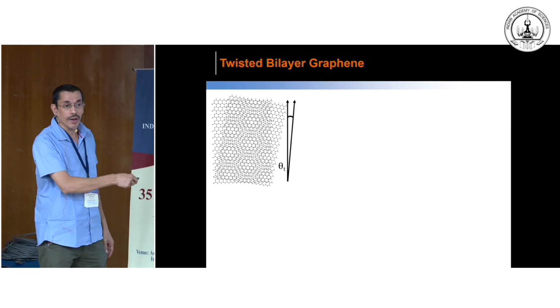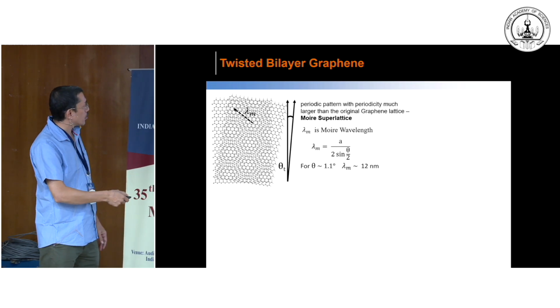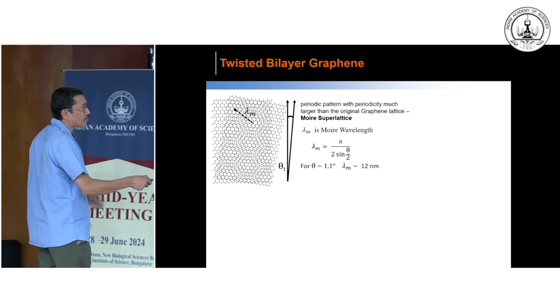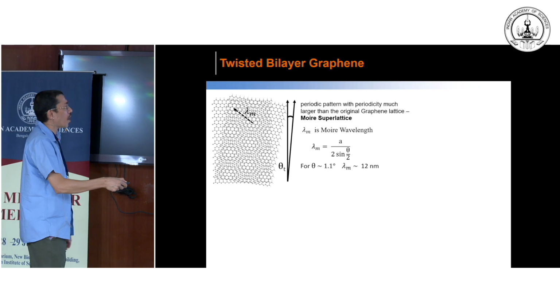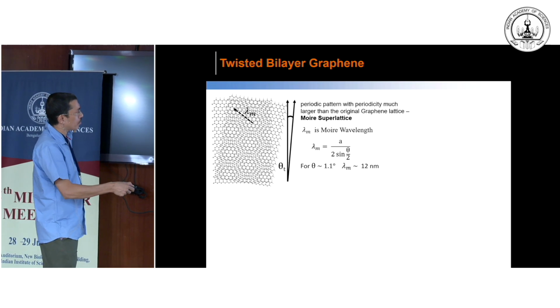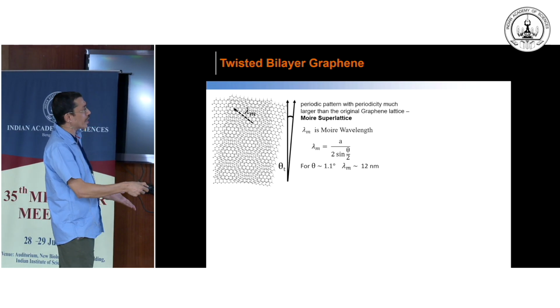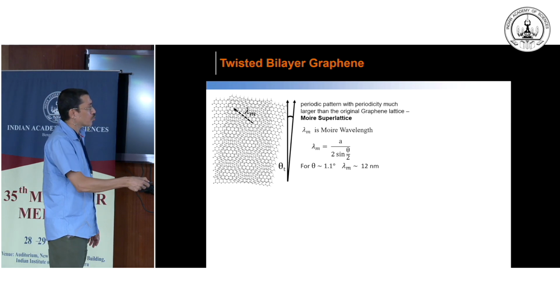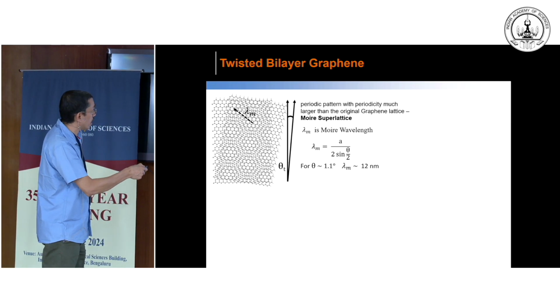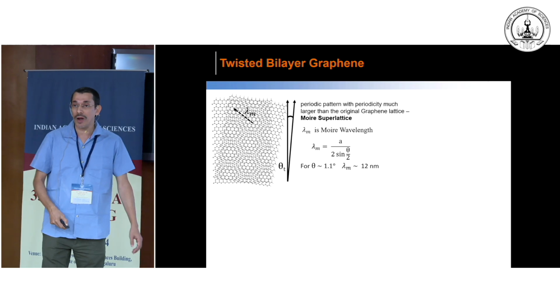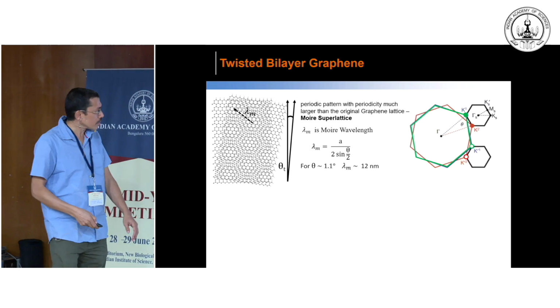As this picture shows, you take 2 graphene sheets, and if you give a relative twist angle, you create a Moire superlattice, and you can quantify the Moire superlattice in various ways. One way is to define the Moire wavelength: for example, theta equal to 1.1 degree, the Moire wavelength is 12 nanometer, which is much larger than the original honeycomb lattice of your single layer graphene.